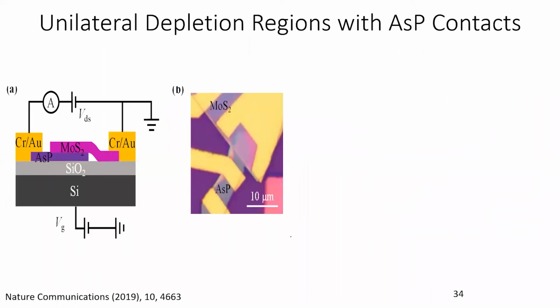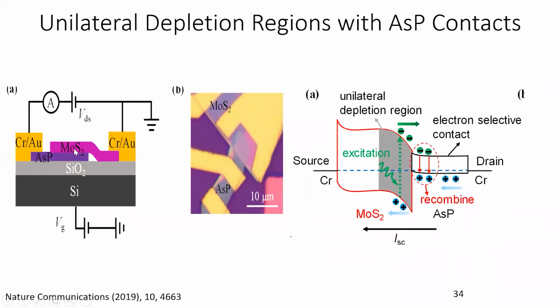Okay, so I would like to speed up a little bit because I'm running short of time, but we have done similar work with another type of contact, this time a smaller gap semiconductor. This is in collaboration with Hu, where we have used arsenic phosphide alloy as a small gap contact to MoS2, where you can get a nearly unilateral depletion region because arsenic phosphide has a much higher carrier density, much more heavily doped. Most of the depletion region is formed in the MoS2.